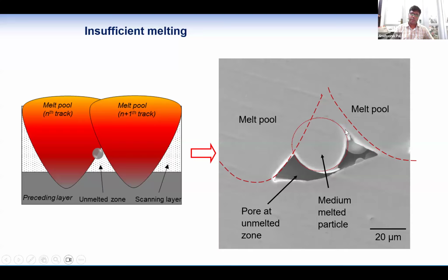And if you look closely here, we can see that a crack can initiate due to, maybe, when during cooling this melt pool will sink a little bit, and this one is also a little bit smaller, right? Then there will be a gap. Due to the gap, a crack can initiate, can occur during cooling, or maybe during the mechanical loading. The crack can initiate from here.